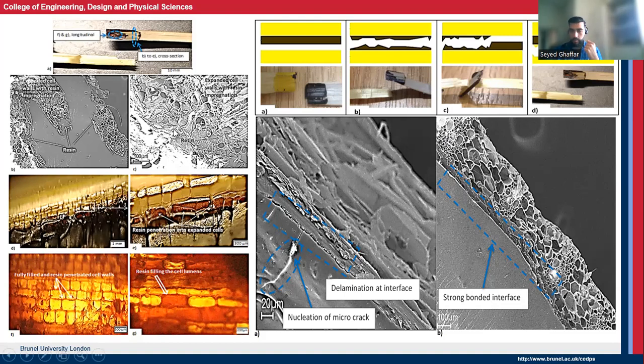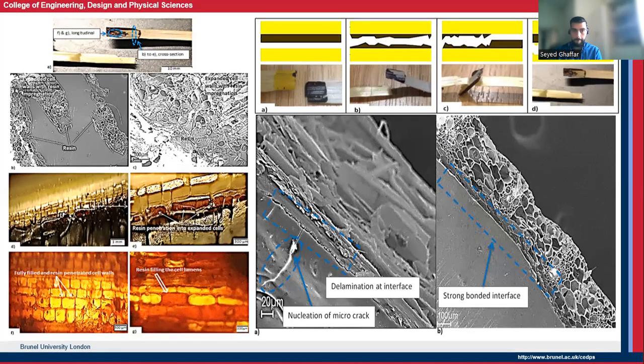Another important point about the steam treatment is the expansion of parenchyma, or let's say the microstructure of the straw, which allows the deeper penetration of the resin into the system, therefore making it stiffer and making it stronger, therefore contributing to a higher performing compressed straw board.